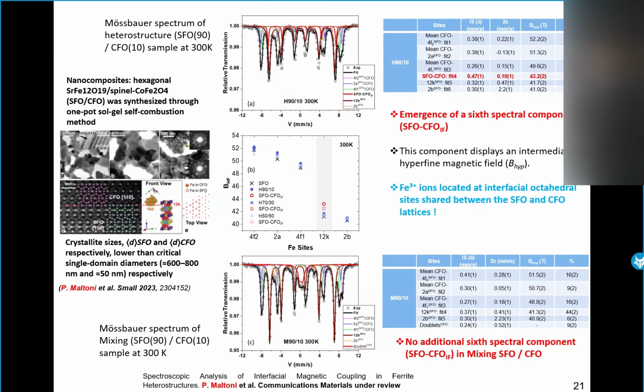But we observe the presence of doublets. I think these doublets come from some isolated magnetic nanoparticles of ferrite, because we mixed the cobalt ferrite with strontium hexaferrite. Maybe we isolate some particles with very small size, and they have a superparamagnetic behavior.